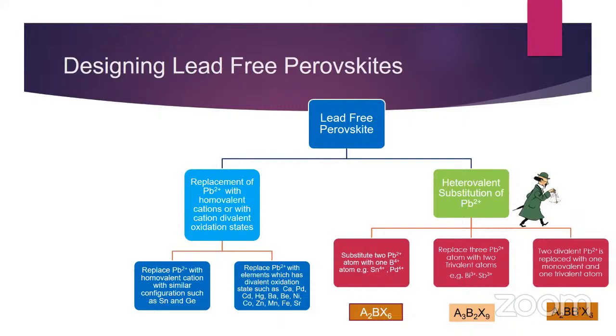Okay. So now scientists have started designing perovskites with two main approaches. Actually, they are trying to replace this lead cation. The first one is the replacement of the lead ion with homovalent cations, or cations which show a divalent oxidation state, that is the +2 oxidation state. So one lead atom can be replaced with a similar homovalent cation which has a similar configuration to lead, such as tin and germanium. And you can also replace the Pb2+ ion with elements which have divalent oxidation states, such as calcium, palladium, cadmium, barium, nickel, cobalt, zinc, iron, strontium, etc.